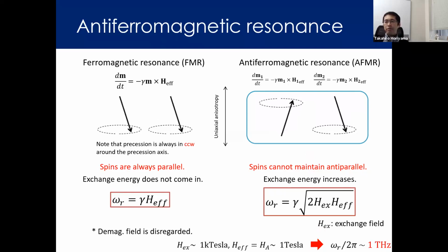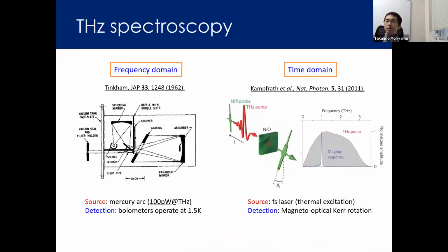This exchange field is typically quite large. It can be up to like 1,000 Tesla in some materials. If you estimate the resonant frequency, it can be up to the terahertz range. Okay. So in order to detect the antiferromagnetic dynamics, we know that we need to do the experiment in the terahertz range, basically.